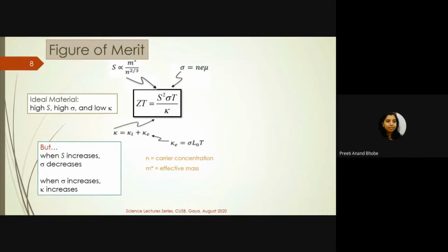The moment I make sigma high, my S is inversely proportional to n. So if I take a very good metal, then S will go down, the Seebeck coefficient will go down. Also, if I take a very good metal, I know its K is very high. Thermal conductivity is good for copper and all. So if this number becomes large, then ZT will be pulled down.